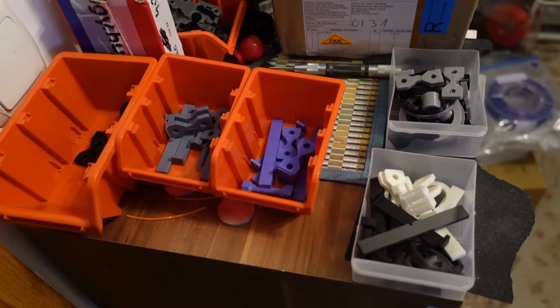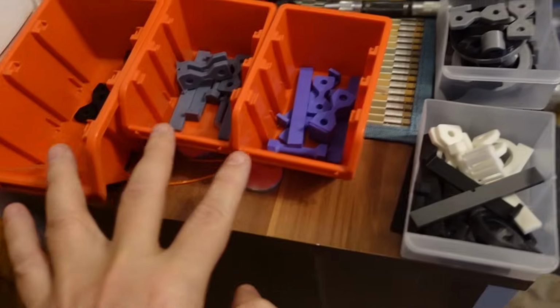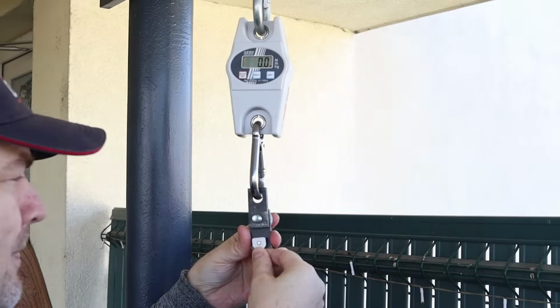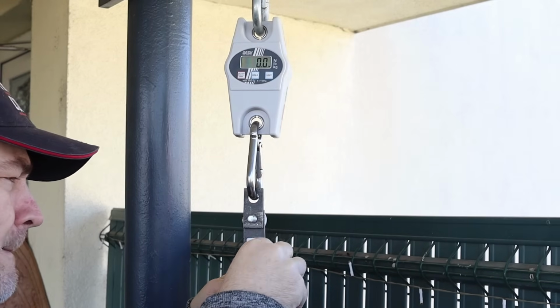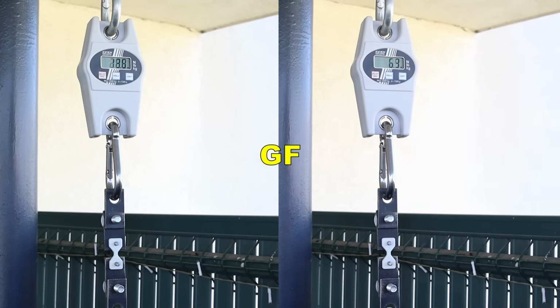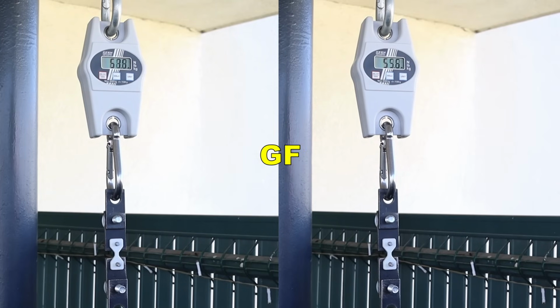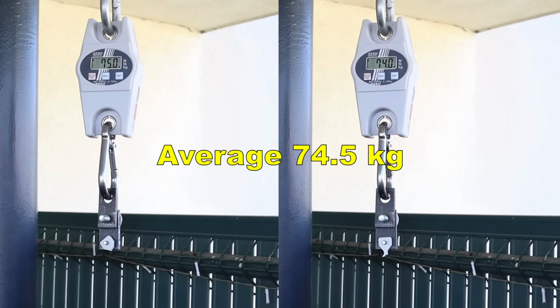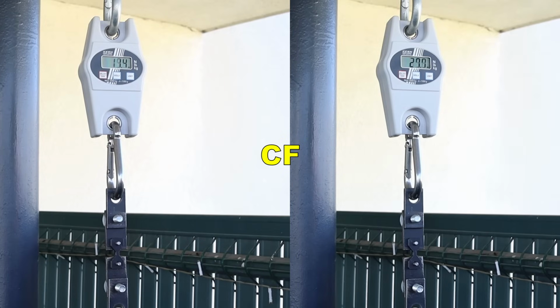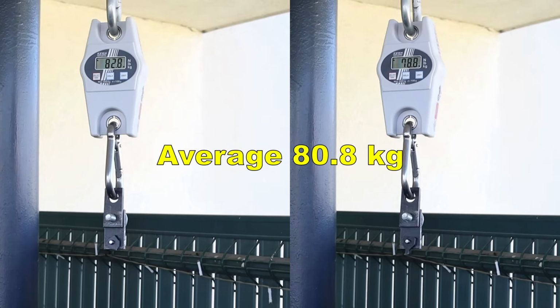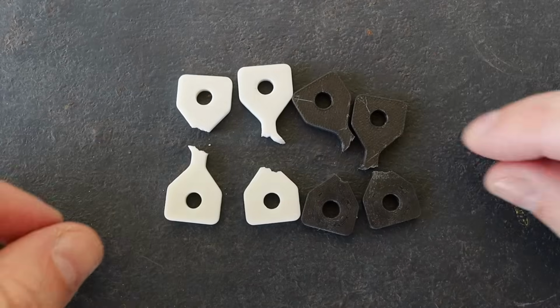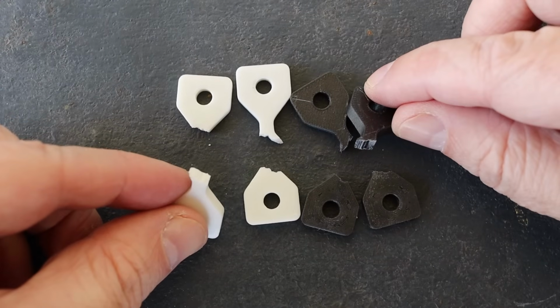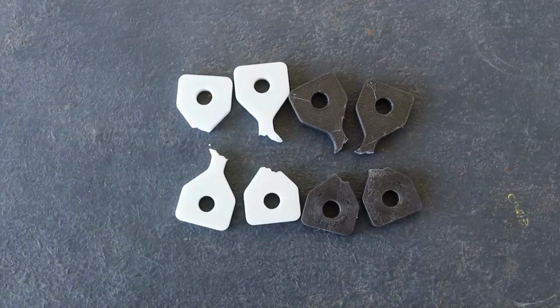I already have several tests in progress, so these are some PLA materials and some TPU filaments. Let's start with the mechanical test. So these test objects are printed in horizontal position. I'm starting with the glass fiber filaments. The average is 74.5 kilograms, the break load, and now the carbon fiber version. 80.8 kilograms is the break load. And they broke more or less very similarly on the smallest cross-section area.